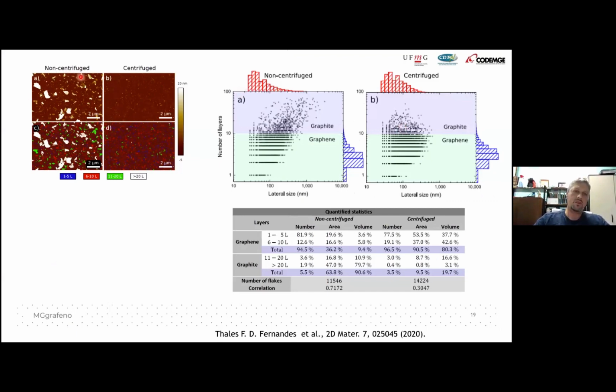So another example is here. We have a non-centrifuged graphene that just came out of the plant, and we have a centrifuged graphene. We see that we get rid of a lot of big flakes here. Okay, and we make this AFM analysis and we measure. This is non-centrifuged, number of layers as a function of lateral size, and we see that we get rid of a lot of flakes here.